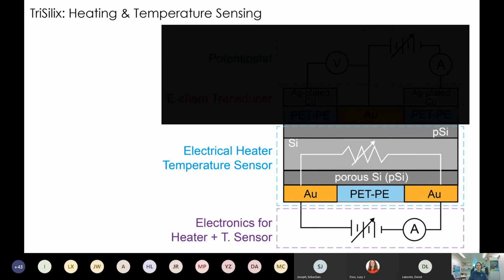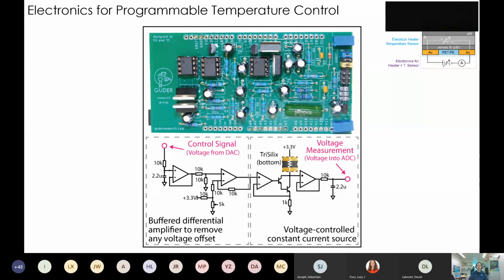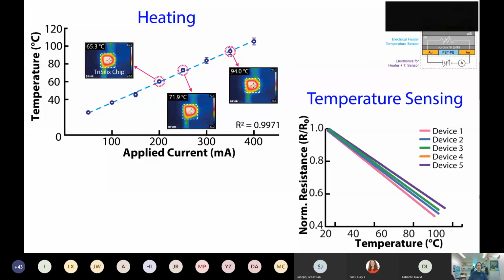So to drive the chip for heating and also for temperature sensing, we have developed some custom electronics in my lab, which allows us to drive an electrical current through the device in a controlled manner, but at the same time allows us to precisely determine the resistance of the device. And if we want to see how well it works, we basically just use the thermal camera to set the temperature of the device, and then maintain the device at a set temperature. So we can essentially modulate the current that's passed through the device to maintain the system at a certain temperature.